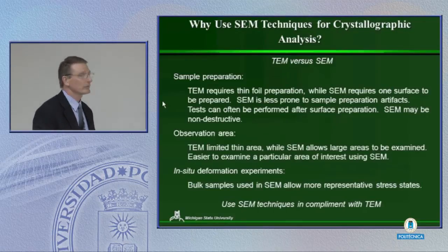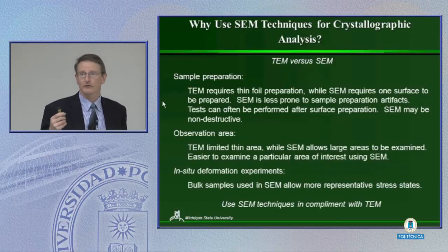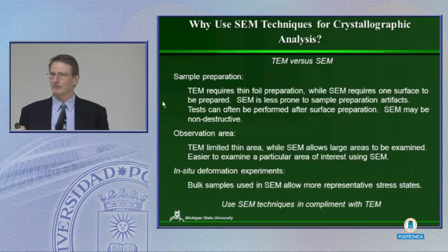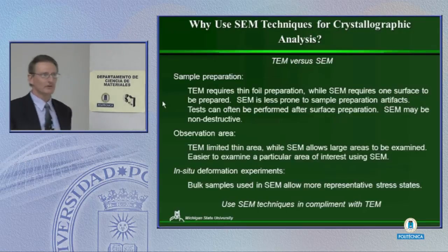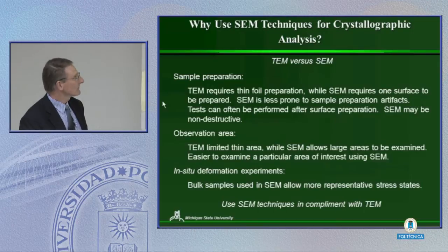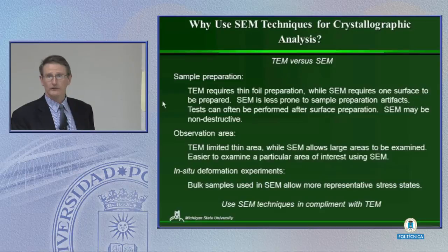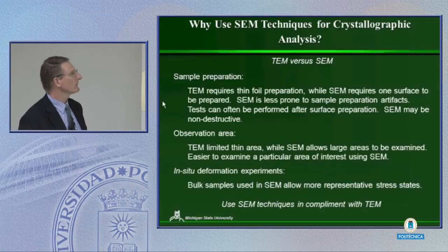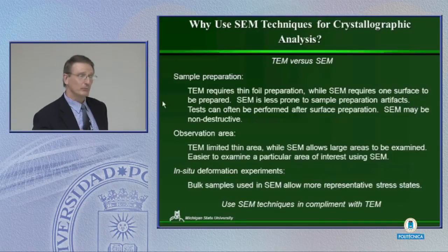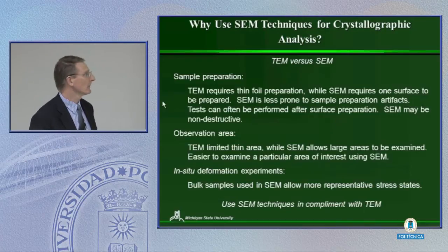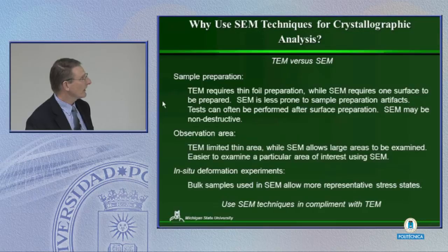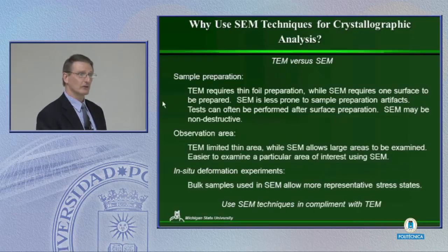So I guess the question comes about, why would we want to use SEM for examining microscale plastic deformation versus things like TEM? Well, first of all, how many people here have ever made a TEM sample? Okay, how many people have ever enjoyed making a TEM sample? Okay. Certainly very difficult, time-consuming. I have a hard time getting students to do this. We have to make a thin foil. SEM really only requires us to prepare one surface. We do have to do a good job on one surface, but because there's only one surface, it's certainly less prone to artifacts. There's more things that can go wrong when you make a TEM foil that may affect your final results. And we can also quite often do tests after we prepare the sample rather than prior to the sample, which gives us a chance to see if the sample is good before we do, for example, a mechanical test. That's more difficult to do with the TEM foil.